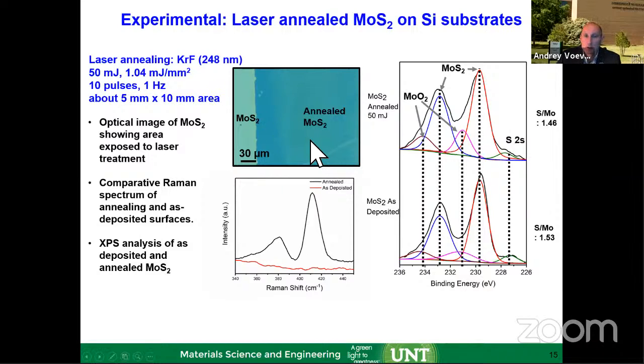And during that process, you're also concerned, if you're doing it in air, how much oxygen you're taking in. If you take molybdenum disulfide and want to anneal it to the crystalline, but you're doing it in an ambient environment, oxygen will come and react with the moly. So you can see the XPS, X-ray photoelectron spectroscopy spectrum, showing the intake of moly oxide formation during the annealing. As deposited, you don't see much of the moly oxide peaks, mostly molybdenum disulfide. And then as you're annealing, you start seeing the molybdenum oxide peak appearing. Again, this was done in air.